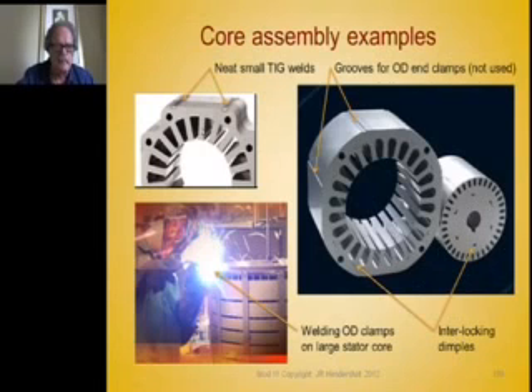This is an example of proper welding of the laminations. That's been TIG or laser welded in those two places, and it's important that you do it over holes like that so shrinkage takes place. There might be some stresses from the weld in this area, but it's not going to make the bore out of round or put any stresses in most of the magnetic circuit. The flux density when the motor's running is very low or almost zero out in there anyway.